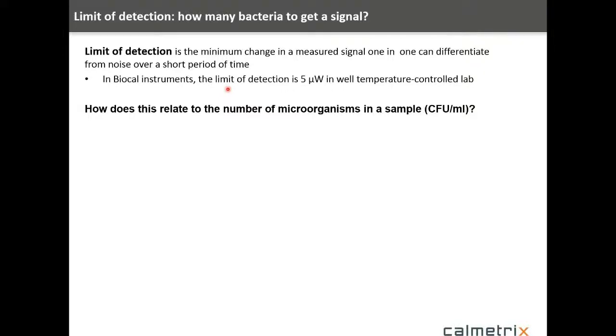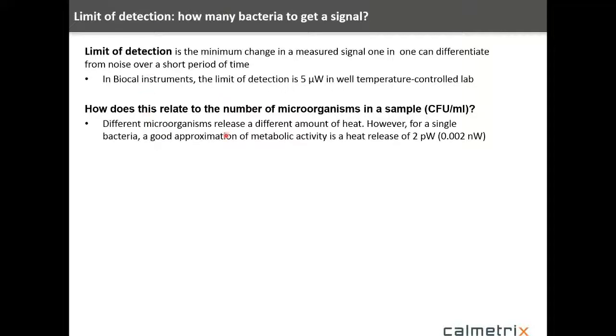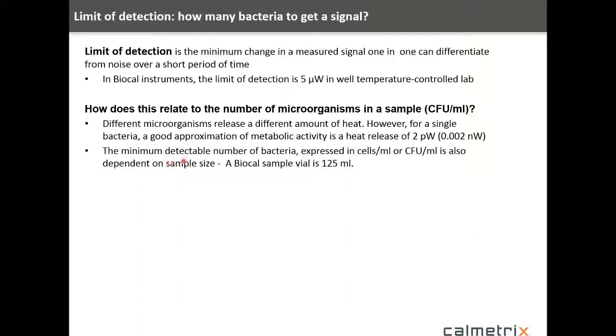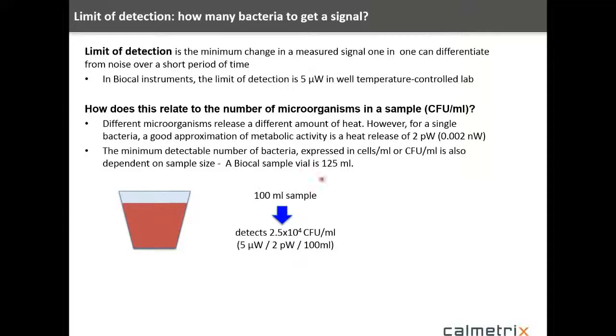So how does this relate to the number of microorganisms that you can detect? Well, different microorganisms, first of all, release different amounts of heat, but if you use a good approximation for a bacteria that it releases about 2 picowatts of heat, that's the first point. Secondly, in terms of looking at the minimum detectable number of bacteria, you also have to consider the sample size. So in our calorimeter, we've got a 125 milliliter sample vial. So if you consider that you can use, say, a 100 milliliter sample, and you work through the math in terms of the 5 microwatt limit of detection and the 2 picowatts per bacteria and 100 milliliters, that means we can detect down to about 2.5 times 10 to the 4th CFU per milliliter.